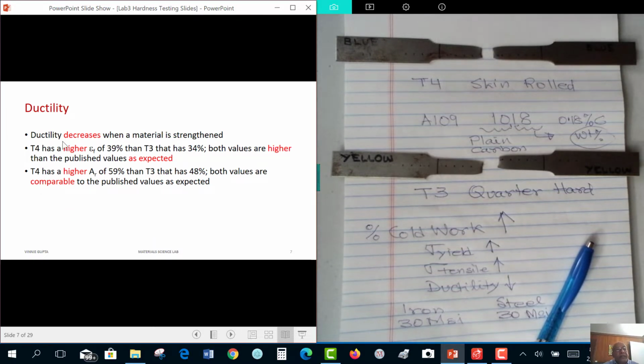Now, what about ductility? We found that ductility decreases when we increase the strength of a material. T4 had higher ductility than T3. That's what we expected. Both values are again higher than published values as expected. Again, in case of sheet steels, often again the manufacturer's ductility is minimum specified. And you found that both values were comparable to the published values in A109.